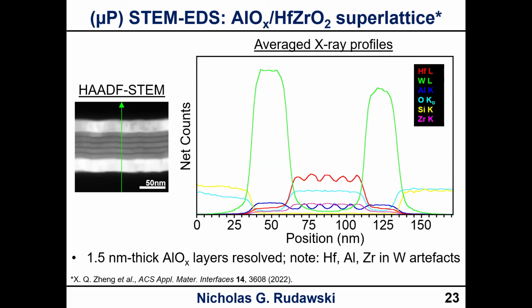And again, we still see the artifacts. It's a little bit more obvious here. You can see very clearly how in the tungsten, the hafnium, for instance, doesn't go to zero. Probably the worst artifact, though, is that you're seeing the aluminum signal in the tungsten, that's basically the same height as where you actually do have alumina.